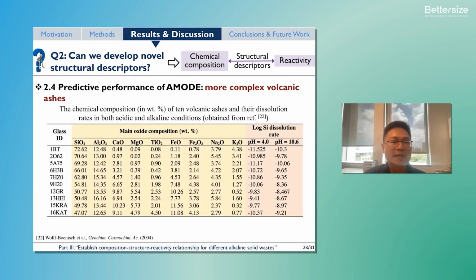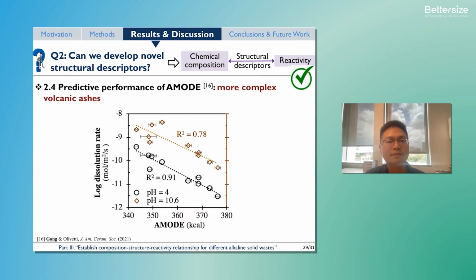We then applied it to volcanic ashes, which have more complex chemical compositions as illustrated in this table. The chemical composition of these different volcanic ashes varies considerably. And because of this chemical variability, the log dissolution rates of these different samples at both low and high pH solutions vary by over 2 orders of magnitude, as you can see in the columns on the right-hand side. Now let's check whether our Amode parameters can capture this significant difference in dissolution rates.